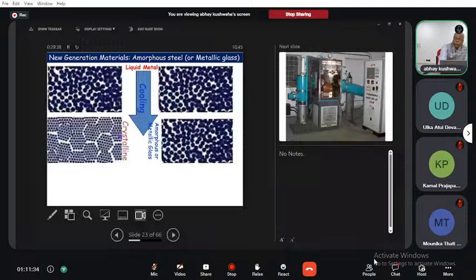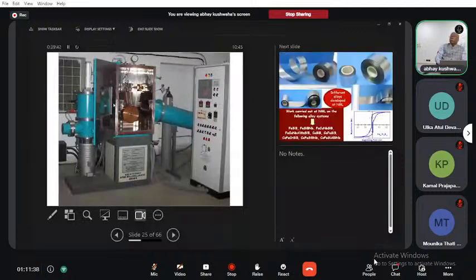How can we do it? We can do it by rapid solidification. What is the process of rapid solidification? You have a copper wheel, and you rotate this copper wheel, and the liquid metal is poured on this copper wheel, and we get a very thin strip, around 30 micron thickness, in the form of a thin ribbon. This setup has the capacity to produce 1 kilogram of material, and it was developed at the National Metallurgical Laboratory.